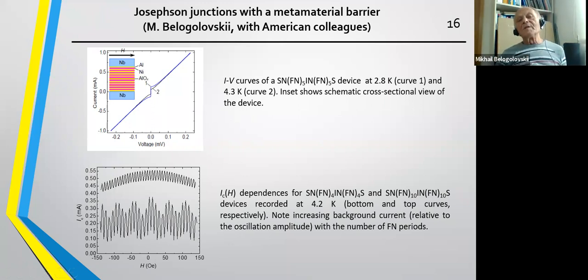So you can see that it's a complicated structure, and even in the center of the structure there is aluminum oxide, so a dielectric. And besides the aluminum oxide, there are also 10 bilayers of such a periodic structure. So in spite of this complicated weak link with a width of more than 50 nanometers, the Josephson junction was observed, but it is not the main strange thing.